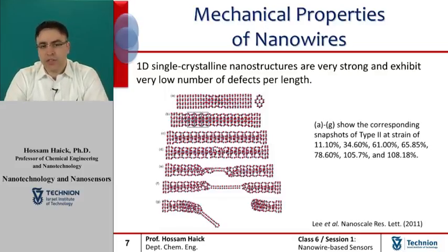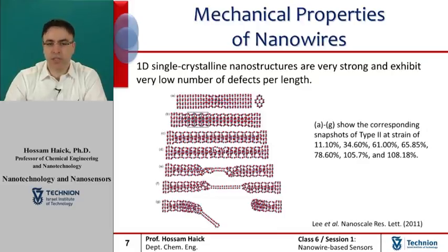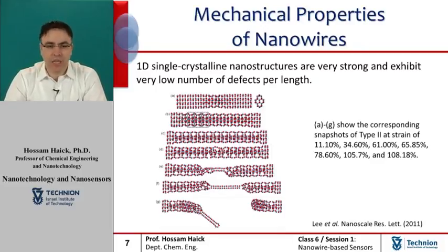At the third stage, the stress increases significantly with a slight fluctuation, and it's even higher than the yielding stress at the first stage. The slight fluctuation is due to the phase transformation near both ends, and the significant increase in the stress is caused by the new phase, as shown in figure C on the screen. After the strain passes the maximum stress, the zinc oxide bond is broken by a yielding stress of 80 gigapascal, as shown in figure D.